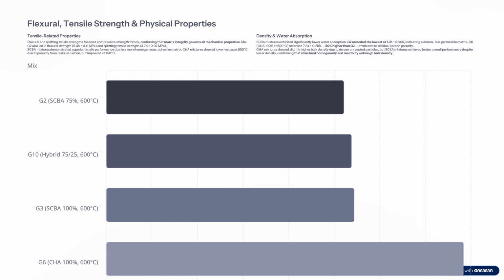Next, flexural and tensile strength and physical properties. Flexural and splitting tensile strength followed compressive strength trends, confirming that matrix integrity controls all mechanical properties. Mix G2 also led to a flexural strength around 5.46 megapascal and a splitting tensile strength of 3.74. SCBA mixtures demonstrated superior tensile performance due to a more homogeneous, cohesive matrix. CHA mixtures showed lower values at 600 centigrade due to porosity from residual carbon, but improved at 750 centigrade.